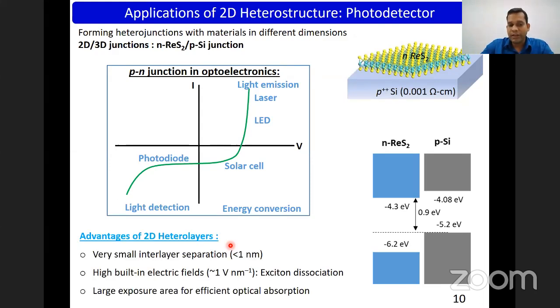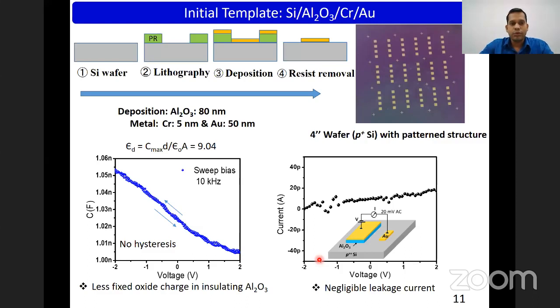And of course, it is a vertical integration. So we have a small interlayer spacing where we can apply a high electric field to dissociate the excitons. And it also has a large exposure area in the 2D surface, so it will have high sensing. To start with this fabrication process, we need some initial template. So we use a 4-inch wafer and use various methods to fabricate the initial template. We do lithography, deposition, and resist removal. Then finally we get the square-shaped structure.